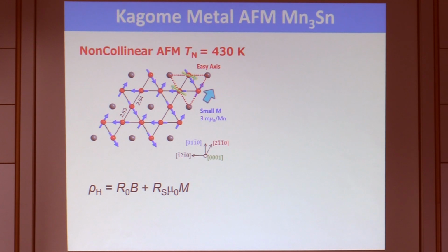And the material we're going to discuss here is this Kagome metal. This Kagome type of metal is quite popular recently among condensed matter physicists, because it's not just a geometrically frustrated system, but often harbors topological electronic structure. So this is one such material. As the previous speaker introduced, the Néel temperature is about 430, and it has this Kagome structure, and spins have a 120-degree order. Nonetheless, it has a small canted magnetization, and that allows us to flip the magnetization. But this is too small to expect any Hall effect.